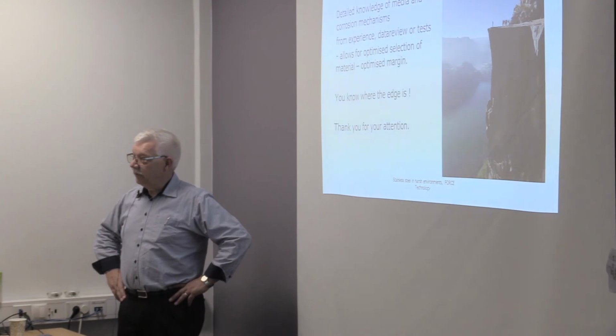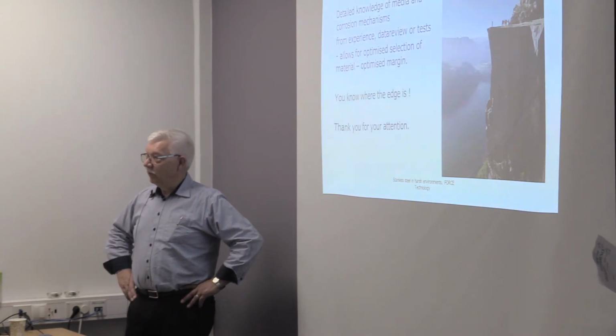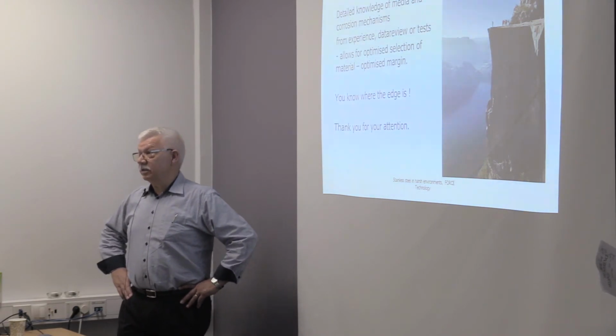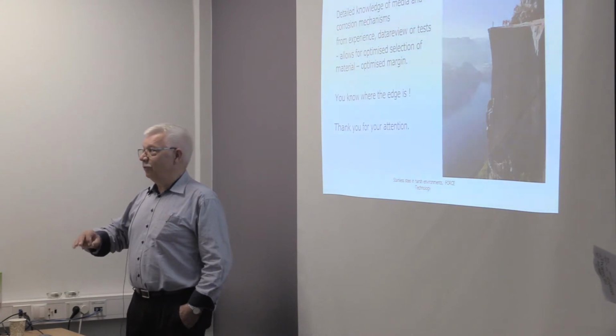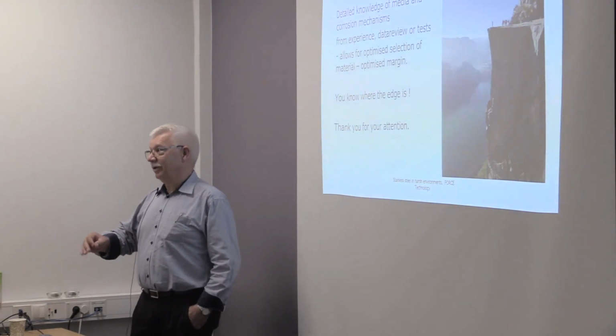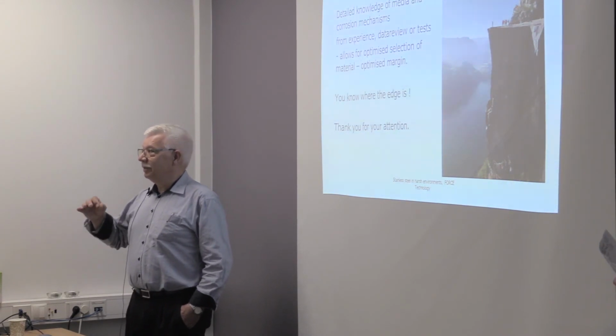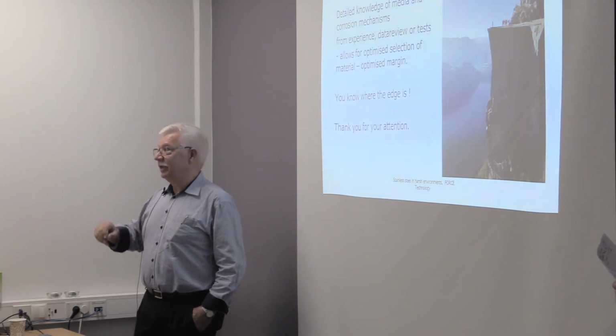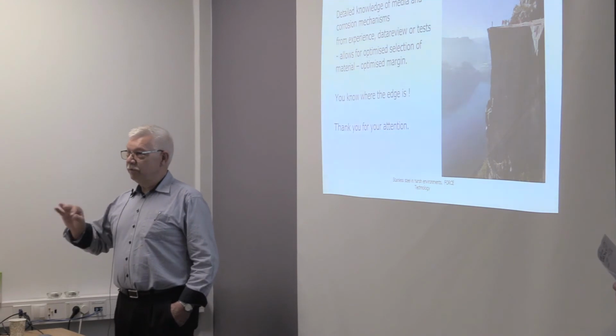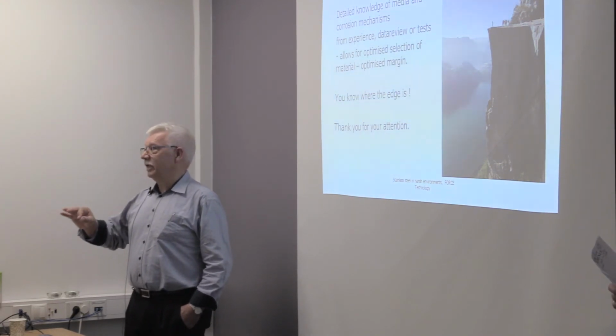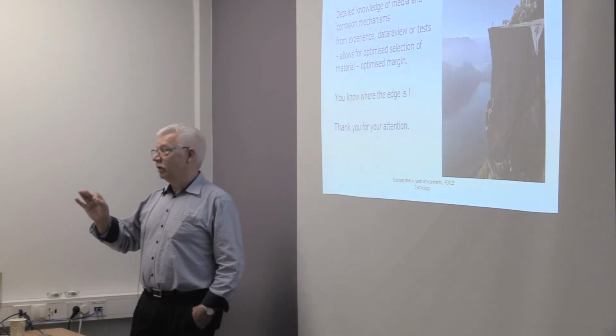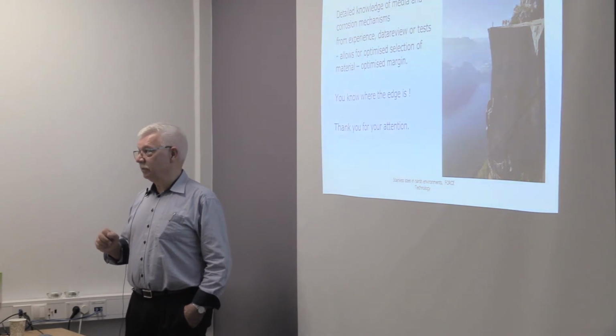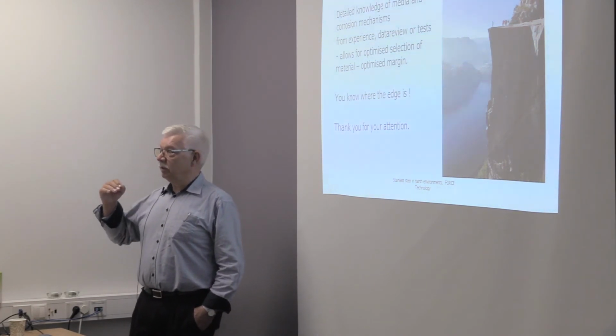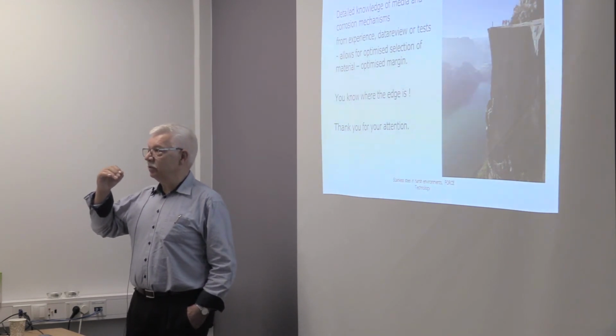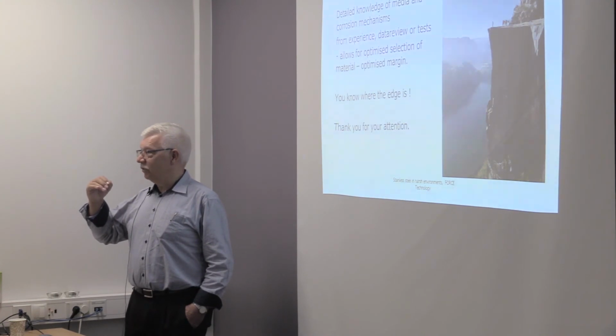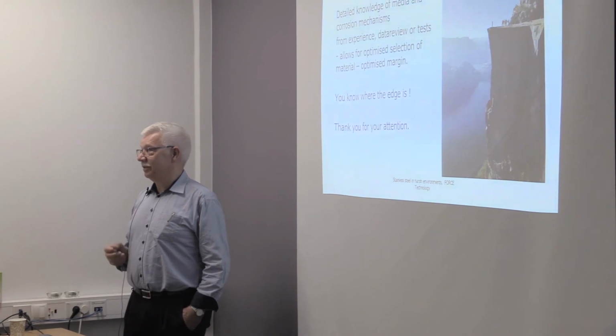Surface treatment of the steel. Yes. Pickling or glass beading effects. Pickling, yes. The best would be to electropolish. From a corrosion point of view, electropolishing would be the optimal choice. Below that, pickling. Because pickling will remove any foreign particles, any slags that could cause problems, it will even take micro crevices from the surface, and that way it will be more resistant. Of course, you have to do it in a way that you don't increase the roughness too much. So a proper pickling would be the best.